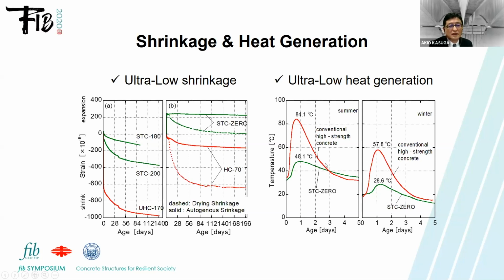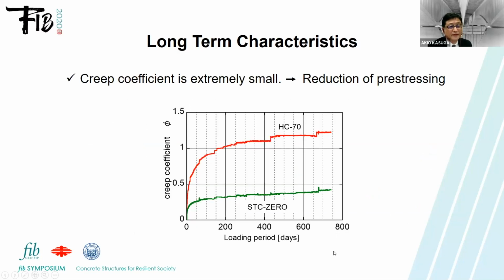And also the heat generation: in summertime, ordinary concrete temperature rises up to around 70 to 80 degrees, but by using zero cement, the temperature is less than 50. In the wintertime, less than 30. Which means no cracking during hardening, and no cracking during curing, which means high durability of the concrete, not only low CO2 emission. Okay, the creep coefficient is around 1/3, which means we can reduce the prestressing materials compared with the normal type.